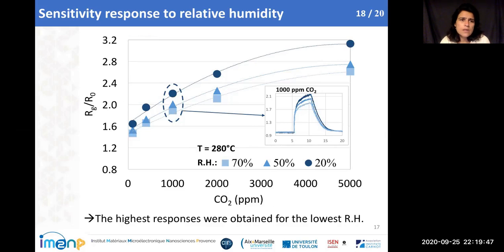If we study the response versus different relative humidity, here you can see that the highest response is obtained for the lowest humidity. Here you have also a zoom on this part. For 1000 ppm of carbon dioxide, the higher response is for 20% of relative humidity.